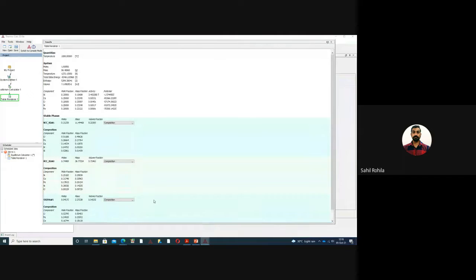But look here, as I have changed from manganese to aluminium, it showed that two different BCC phases are present at that point, that is 1000 degrees centigrade, among which one is a chromium rich region, and another is a nickel and aluminium rich region, and that is exactly what we are observing through experiments also.